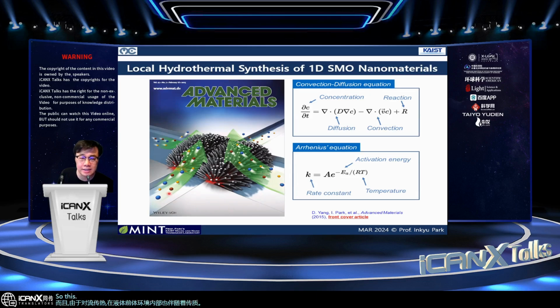So this little circle symbolizes the fresh precursors that are supplied continuously by the convective mass transfer. So this convection and also diffusion governs the transport of the precursor to this local hot zone. And in this local hot zone, we use the endothermic reaction. High temperature will generate a higher chemical reaction.